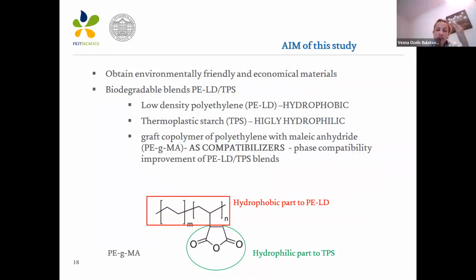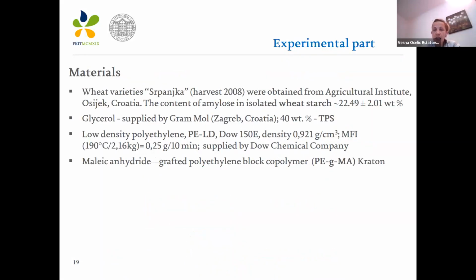In our research, the compatibilizer was a graft copolymer of polyethylene with maleic anhydride. Why? We can see in this structure of the compatibilizer that the grafted maleic anhydride is the hydrophilic part, which is compatible with TPS, and polyethylene is the hydrophobic part that loves the polyethylene. This is the material that we use in our research.